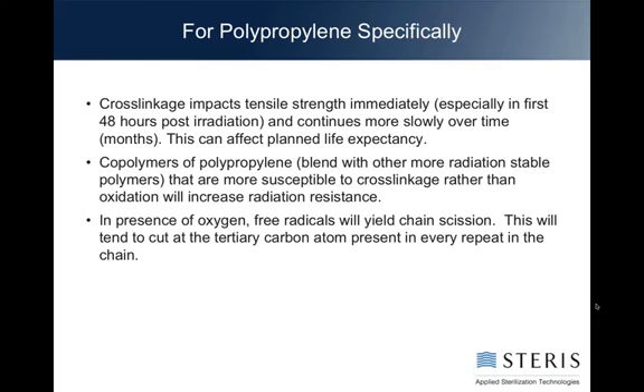For polypropylene specifically, it's actually a very phenomenal material when you start looking at it as a chemist or as a scientist, that something so simple can create so many different phenomena. Okay. What we see here is that with polypropylene specifically, cross-linkage will impact tensile strength, so how strong that thing is when you press against it, especially in the first 48 hours post-irradiation. That cross-linkage function will continue, but more slowly over time, even over months.